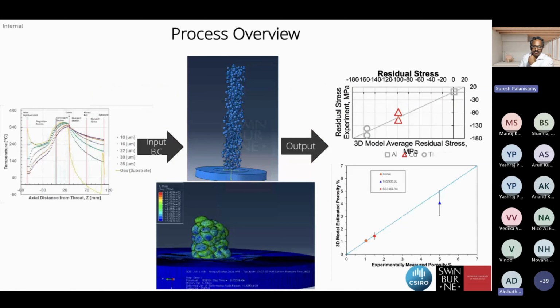So this is a very important finding because, as I told you, achieving this layer thickness, this multi-layer thickness, is very hard. People have done one layer or two layers maximum, not this many layers. And the maximum we have seen in the literature so far is 400 particles or something like that. So we achieved 10,000 particles, which is a significant number of particles deposited. That shows how difficult this work is.